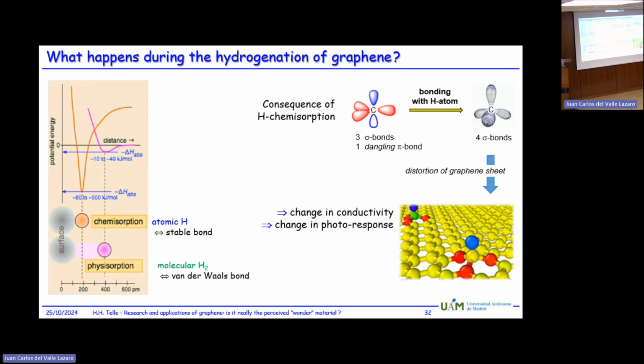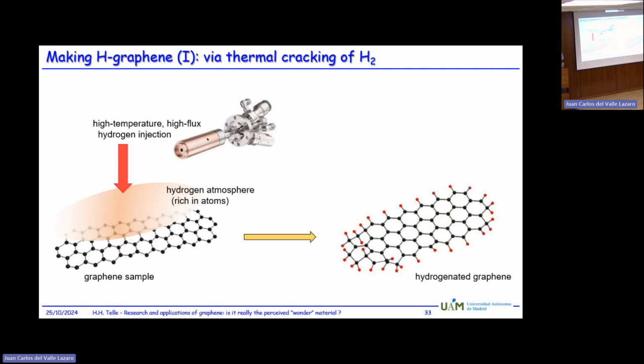So how do you do that? Because normally we know that hydrogen will exist only in molecular form if we don't do anything to it. So there are two methods to produce the hydrogen atoms, which are necessary for the chemical bonding. One is by thermal cracking. So there are commercial devices available which enable you to more or less crack the molecules and get hydrogen atoms.